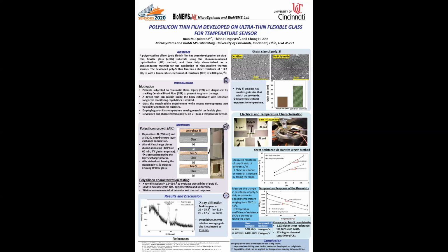In step 3, the exposed aluminum on top is removed by using an aluminum etchant, and afterwards, we started doing several tests to characterize the material's functionality as a temperature sensor. By doing an XRD, SEM, TLM test, we can characterize for crystallinity, grain size, and electrical response of the material. As we can see in the graph, we have peaks at 2 theta equal 28.5 degrees in the 111 direction and 47.5 degrees in the 220 direction. Confirming crystallization was successful, and by using the Scherrer relation, we calculated an average grain size of 21.6 nanometers.